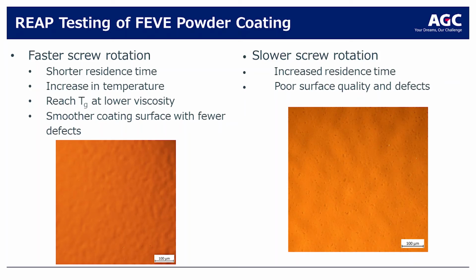So what you have is a smoother coating with fewer defects on it. If you look at the one on the right with this screw rotation, you can see the little holes in the surface, and this is created because you're getting poor surface quality and defects in the coating. Well, when you have a defect in the coating, this can let those corrosion initiators come through. So that's the reason we did this first on powder, because it's a little bit easier to see, and there's more of a contrast between the two.